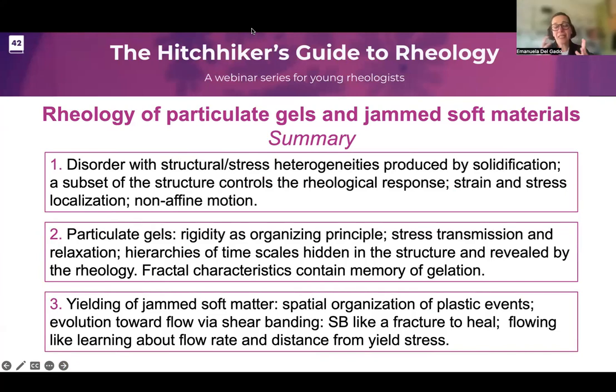So basically, I wanted to highlight how important it is to understand the disorder and the structural heterogeneities and the stress heterogeneities. Without this, we cannot make sense of the rheology. And in fact, when we do this, we realize that even when we image all the structure, we need to understand what is the subset of the structure that in fact controls the rheological response. And this is crucial to identify the regions where strain is localized, where stress is localized. And some of this information is contained in the non-affine motion.